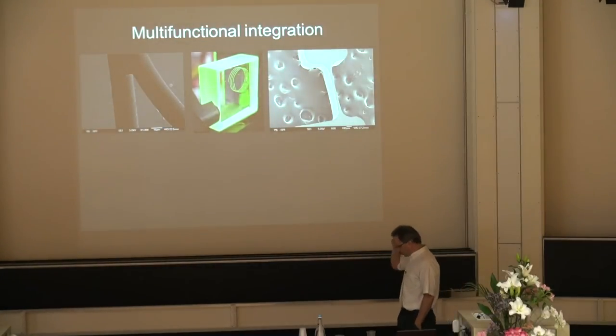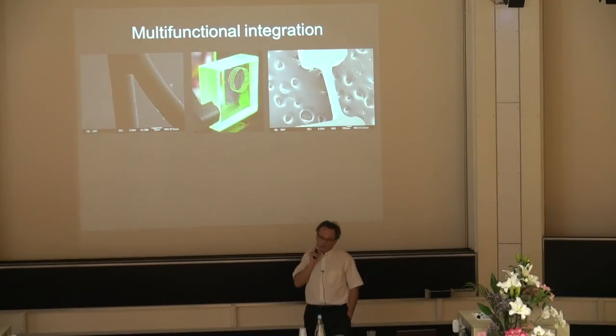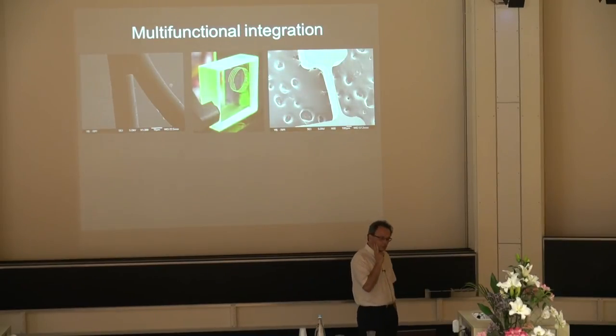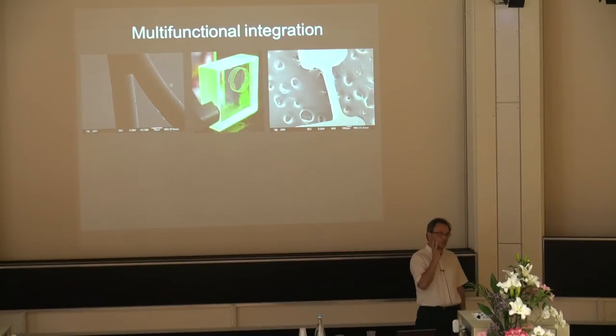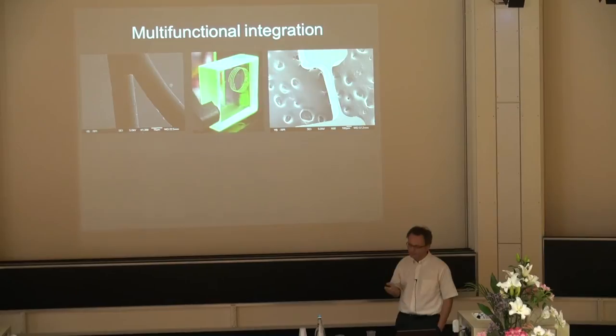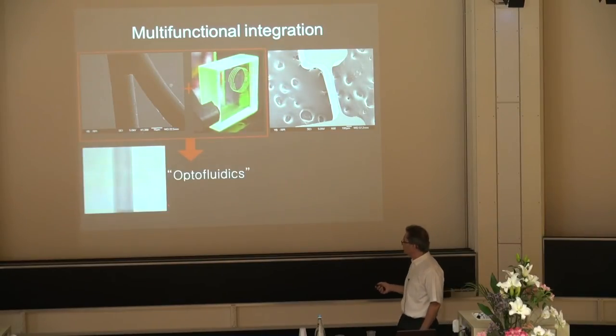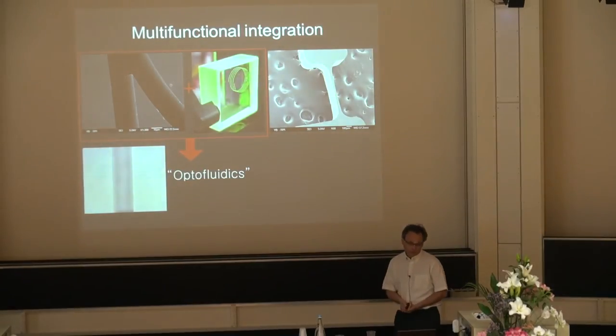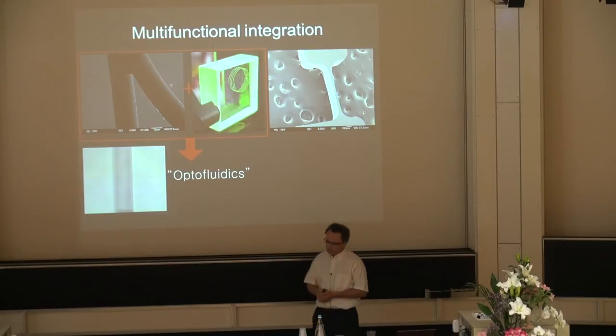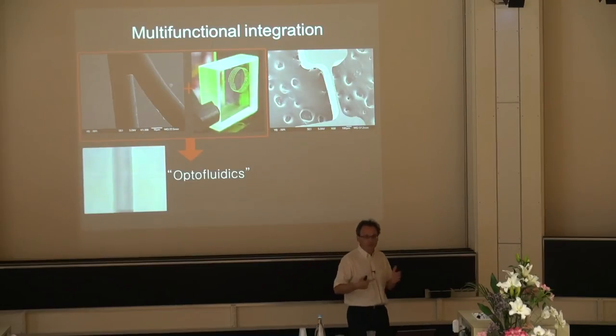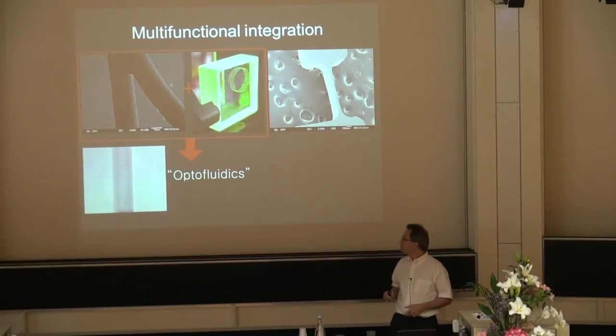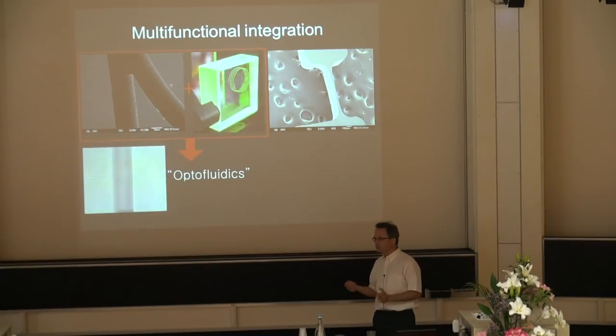Now, I'll stop that with microstructures, but just finish up with some examples of how we can use that in microsystem multifunctional integrations, basically. As I mentioned, you can have fluidic channels and then waveguides, and if you combine them, you form some optofluidic device. Now, why is this nice? Because this is made in one sequence. You do everything at one time. You don't use one system to make the waveguide, another one to make the fluidic channel. You make everything in one go.